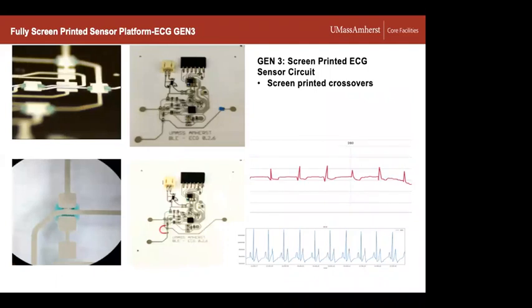So now stepping back a little bit, we want to go to more sophisticated printed electronics, again, before we attach the silicon devices. And in many cases, if you look at the circuits here in the middle, both top and bottom, you see some headers, which are the black plastic component on the top with leads that come in. We've got a yellow component, and then we've got a series of surface mount components in there. Now, what we wanted to do was have something where we could print the crossovers. What we've done previously is we just have pads that come up to a crossover area, and then we take a surface mount component. We call it a 0 ohm resistor. So it's basically just a bridge that we create over that, but we have to hand assemble that. So that's no way to do it.